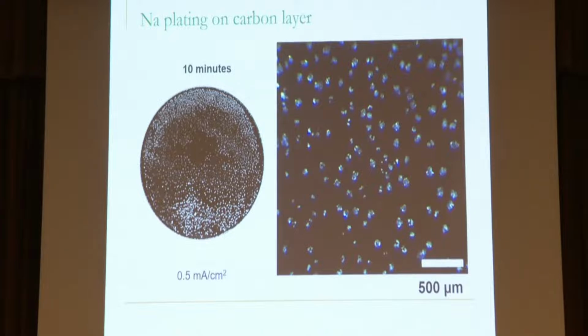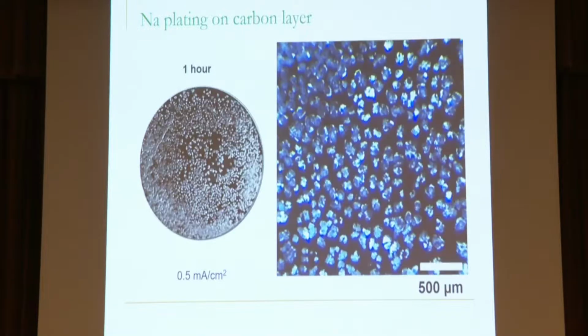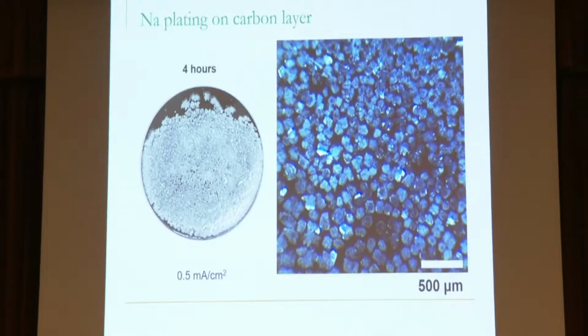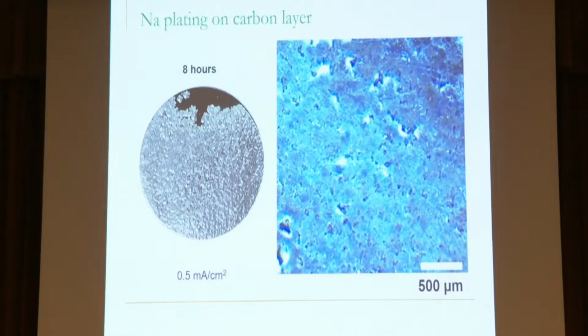So this is optical microscope images of sodium plating on carbon. When we first do this at a current of 0.5 milliamps per centimeter squared for 10 minutes, you see these little nuclei. So this is in the optical microscope. These are sodium with a background of carbon. We plate for a little longer. The sodium grows. A little bit longer, grows even more. A little bit longer, we get this really nice uniform film at 8 hours of growth.